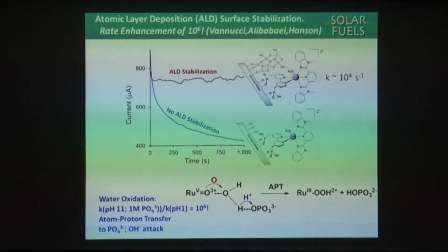The first value of this ALD surface stabilization is here. Same carbene catalyst, but now in two versions. One, just a version on a surface. Now I've increased the pH to pH 11. So this complex doesn't have a chance on the surface. It undergoes rapid hydrolysis, you can see that. If you put it on the surface and hold the potential high enough to do water oxidation, the current starts high and it just collapses. The stuff's coming off the electrode.